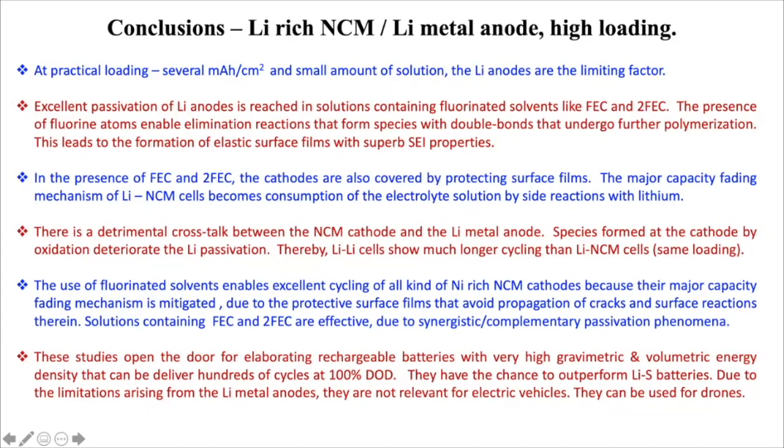Now, concluding the lithium-rich NCM lithium metal anode, high loading. I mentioned and emphasized the high loading. Practical loading means that we're talking about several milliamp hours per square centimeter and a very small amount of electrolyte solution. I didn't emphasize it too much, but it appeared on the slide. So when we say practical loading, we mean both several milliamp hours per square centimeter, and also a very small amount of electrolyte solution. So the lithium anode is the limiting factor.